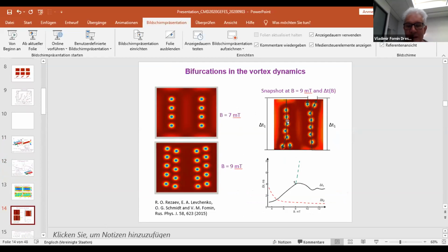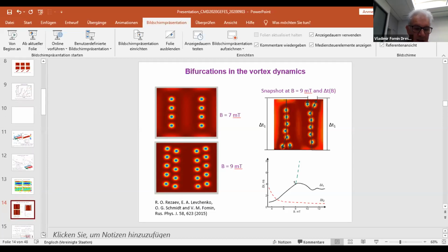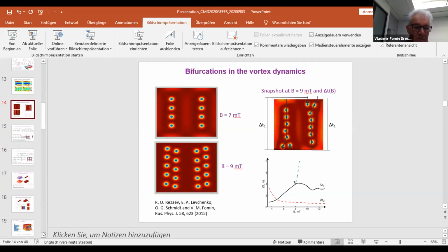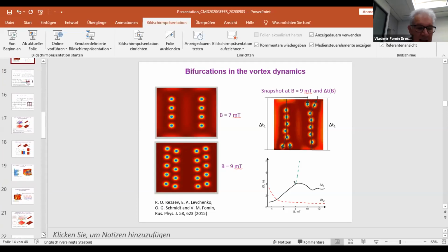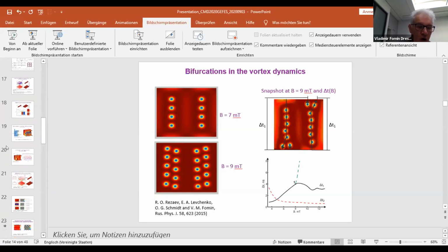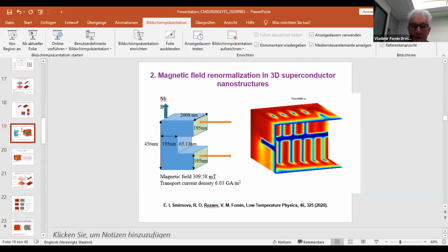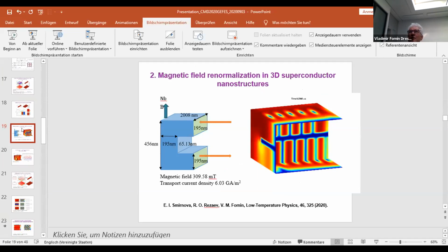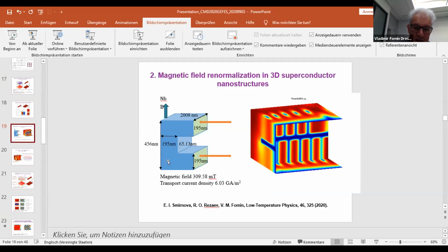So in some part of the tube, there is only one chain, in some there are two chains, and there is a transition. But this is only when the current is not so strong. Our recent calculations, taking into account magnetic field renormalization, show that the nature of these vortices is different, dependent on the distance between the upper and lower parts of the structure.